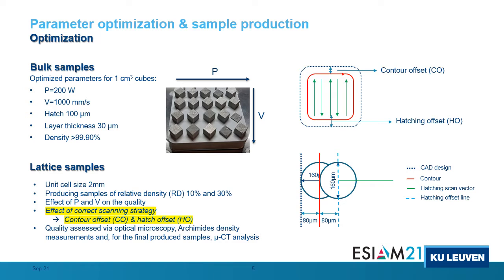The optimization process has been performed for 2 different relative densities, namely 10% and 30%. We started from the optimal parameter set for bulk coupons and we investigated the effect of the laser power and velocity on the metal lattice structure parts. Moreover, in order to produce lattice structures that are closer to the CAD geometry, 2 scanning strategy parameters are investigated, namely the contour offset and the hatch offset.